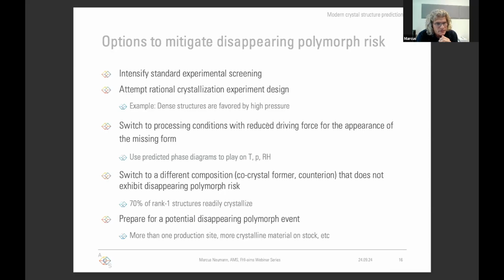When the chemistry is not 100% nailed down, for instance, when pharmaceutical companies work with co-crystals or with salts, where there's a certain leeway on the co-former, on the counter ion, there's actually also another option, and the other option is to try to change the co-former and the counter ion to get onto another landscape for different chemical species, different chemical compound, and that landscape then would not exhibit disappearing polymorph risk.